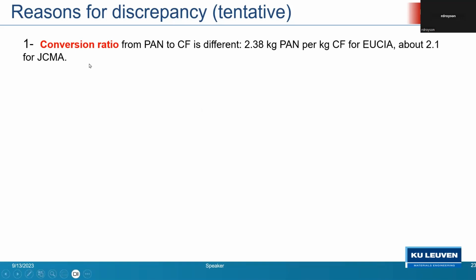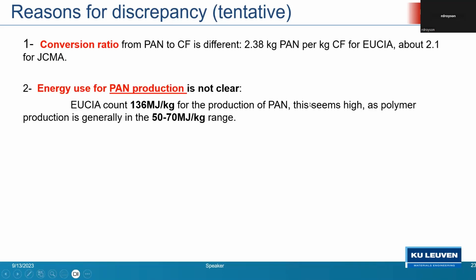First, the conversion ratio. EUCIA is assuming that you need about 2.4 kilogram of polyacrylonitrile for 1 kilogram of carbon fibers, whereas JCMA measures in their plants a conversion ratio of 2.1. Of course, it's in their interest that that conversion ratio is as low as possible, because the lower it is, the lower the amount of polyacrylonitrile fibers you need for producing 1 kilogram of carbon fibers.